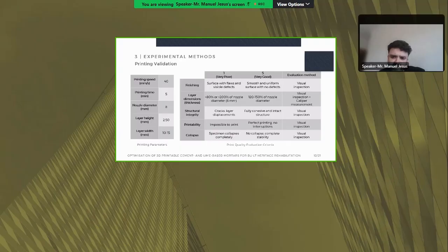And to ensure a consistent and objective evaluation of the printing trials, we also established a qualitative scoring system, as you see in the table on the right, based on 5 indicators: finishing, layer dimensions, structural integrity, printability, and collapse. Each criterion was rated on a scale from 1 to 5, where 1 was very poor and 5 was very good. And the final result was achieved with the arithmetic average for each formulation.